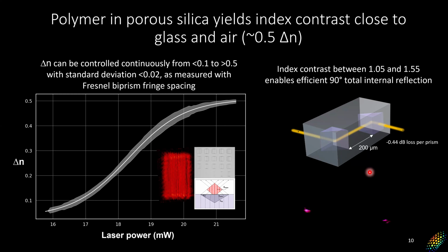How do you stop the polymerization? You've got the two-photon polymerization. Is there any issue with aging and exposure? Not that we've seen. We have samples like these with these prisms that we've left and aged for a few months now, and we take them out every now and then and measure them, and we haven't seen any difference. But if you're using them actively, and probably at a different wavelength, obviously,